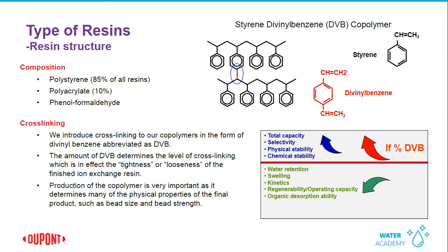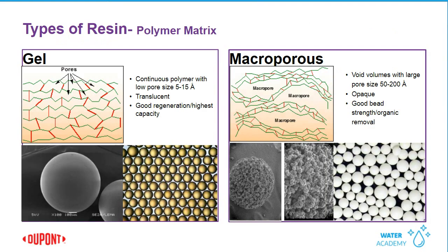We offer resins with two different types of polymer matrices, a gel matrix or a macroporous matrix. Let's look at the gel resin on the left-hand side of your screen. If you look at the micrograph, you see a very smooth surface to this resin. And if you were to look at it under an optical microscope, you would see that the resin is translucent. This resin has very low porosity. The only pores are the space between the polymer chains, which is only about 5 to 15 angstroms. This resin, though, has a very high capacity and very good regenerability.